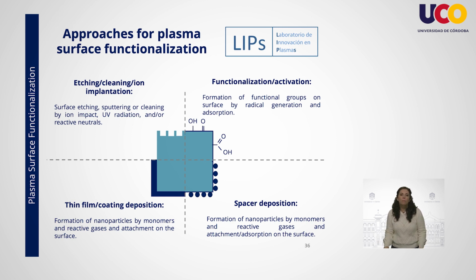or hydrocarbon-based substrate material. As an example of the importance of surface chemical reaction, let's consider 3 active species: the carbonyl group, the hydroxyl group, and the carboxyl group. The chemical attachment of these groups to hydrocarbons or polymers affects such surface energy-dependent properties as wettability, wickability, and printability of polymeric materials. The deposition of plasma-generated nanoparticles as spacers of the surfaces in a single process step is another promising functionality, for example, to modify the roughness of a surface.